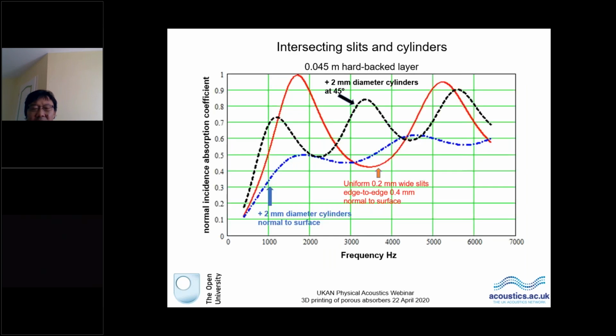So I had a go at seeing what you could do to try and reproduce this by having intersecting slits and cylinders, because basically if you take a set of slits and you perforate them, then you've got intersecting slits and cylinders, at least to my naive way of thinking you have. But of course it gives something that's quite different from what's predicted by Thomas and his student. And even if you incline the perforations, it doesn't produce the same kind of effect. So something else is going on, which would be quite interesting to investigate.